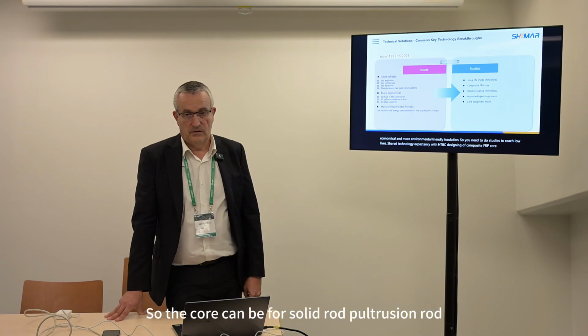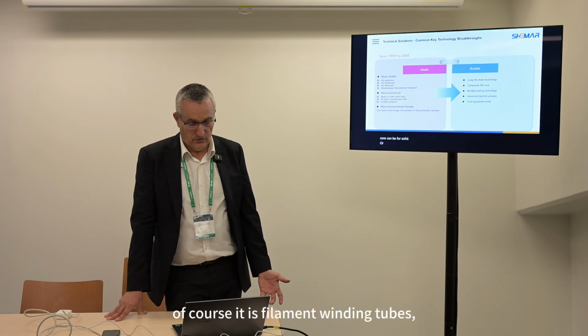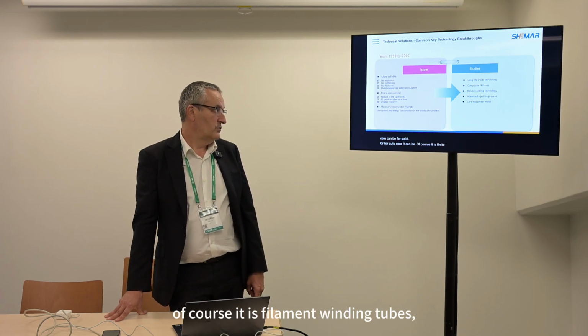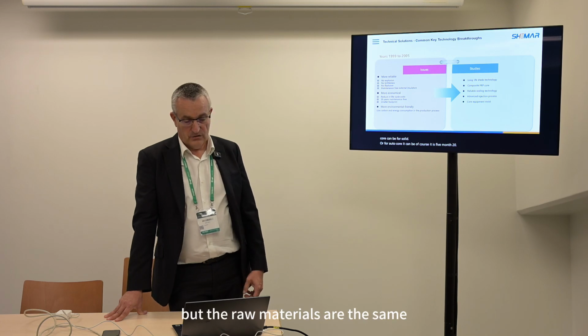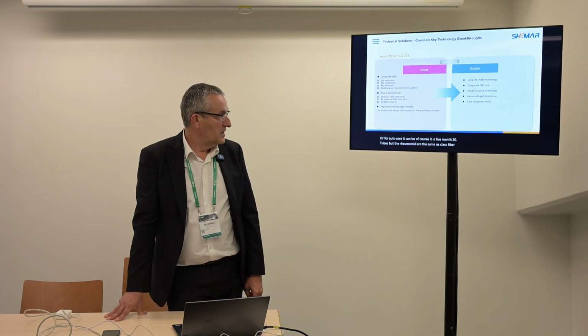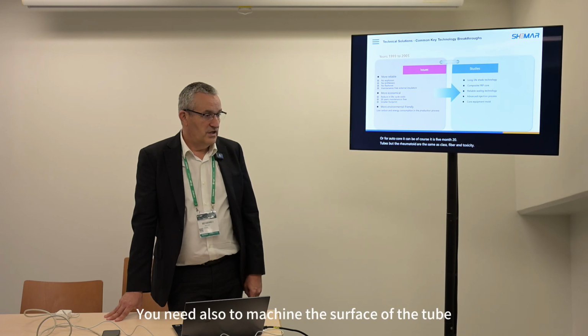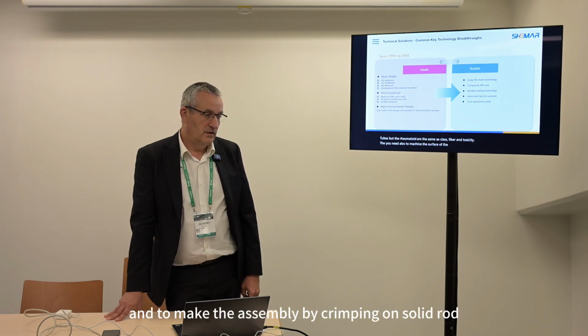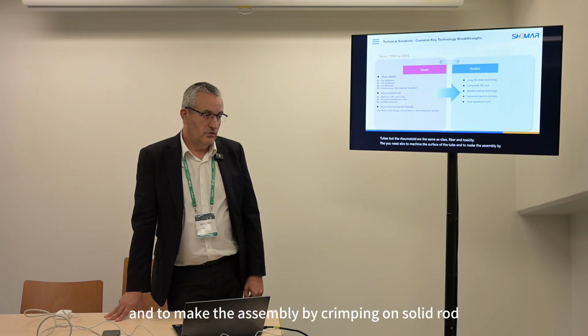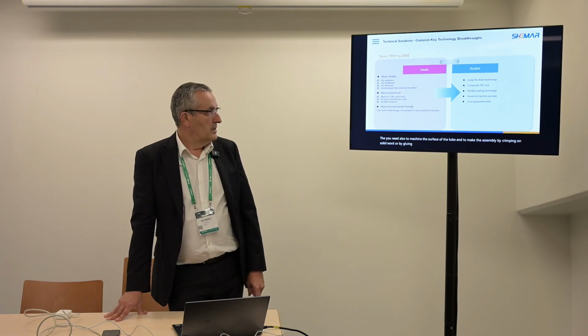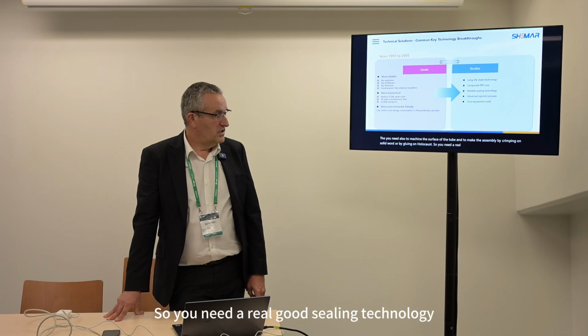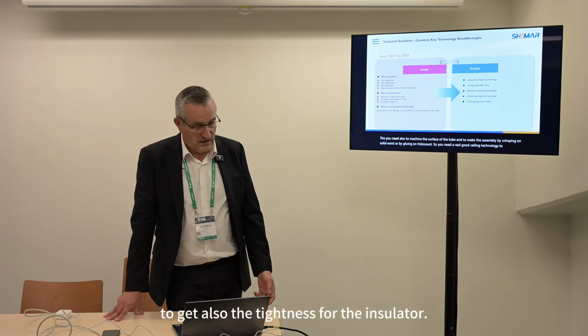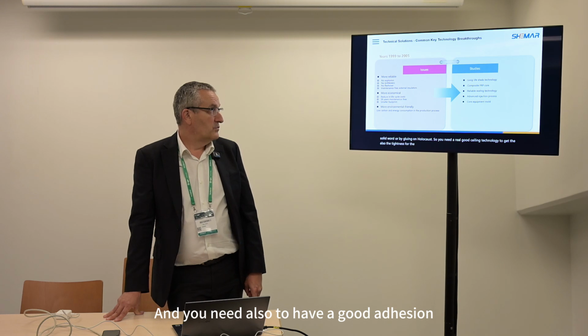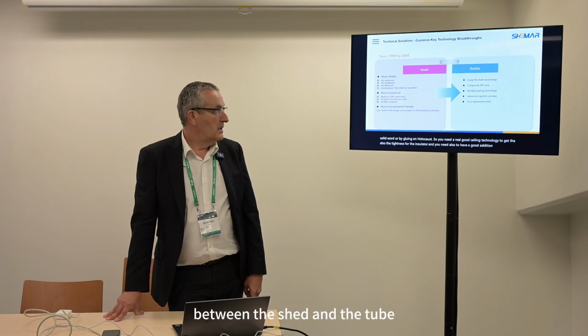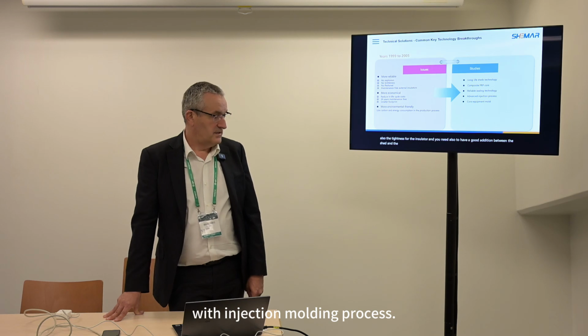So the core can be a solid rod, a pultrusion rod, or a hollow core, which is of course filament winding tubes. But the raw materials are the same: glass fiber and epoxy resin. You also need to machine the surface of the tube and make the assembly by crimping on solid rod or by gluing on hollow core. So you need a really good sealing technology to get the tightness for the insulator. And you need a good adhesion between the shed and the tube with the injection molding process.